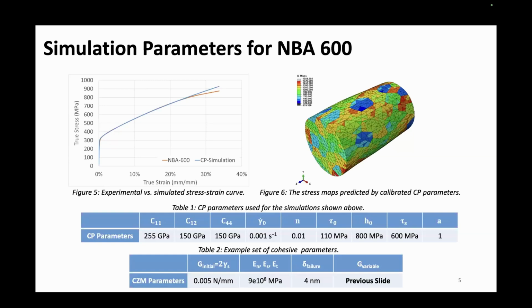So we first calibrate the crystal plasticity parameters with the tensile data provided by sponsor Jivkov. The calibrated parameters used in this simulation are shown in table 1. On the right-hand side, you can see a stress map predicted by the crystal plasticity model, which shows the stress distribution across the whole microstructure, and also the stress variation along and within the grain boundary, which reflects the effect of the microstructure features.